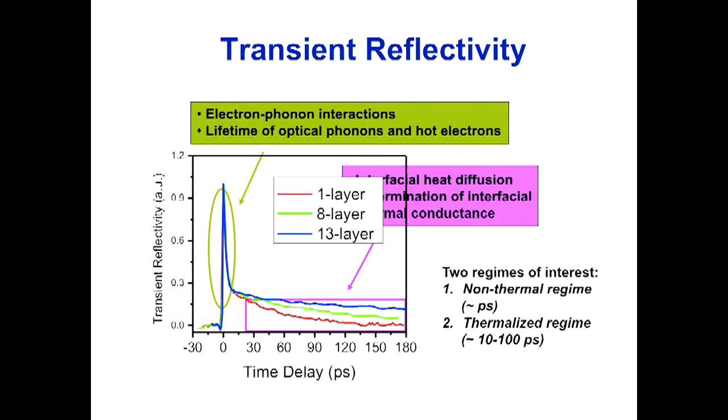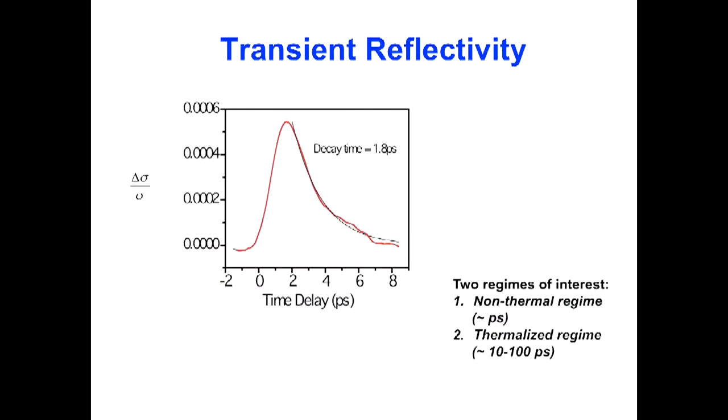Then there's also this much more rapid feature, and that goes more into the kind of fundamental non-equilibrium physics of the system. If you look at this on a little bit expanded scale, you get, again, a rise time that's more or less dictated by the duration of the laser pulse that we used in this case, and then you get a fall off in a time of about 2 picoseconds. So actually, in this regime, there's even more going on.